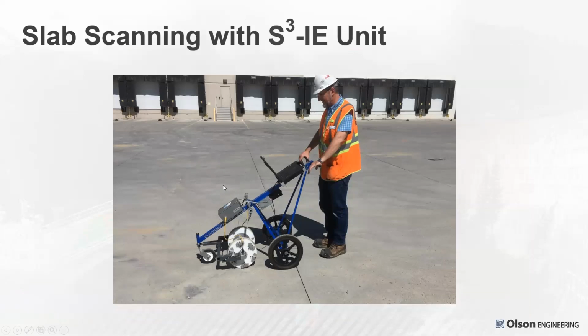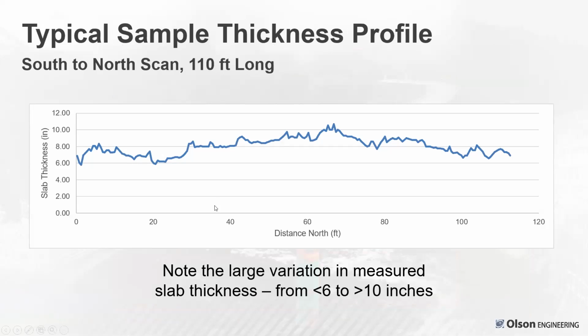Just again, we walk along at a walking speed. And here's a typical profile. This is going north to south along the short axis of the scan area. A single scan. And you can see how much variation there is in thickness as we go along this nominally 7.5-inch thick slab on grade. And this is probably not unusual for a slab on grade, but in this single scan, we have thicknesses from less than 6 inches to over 10 inches. It's quite a bit of variation.